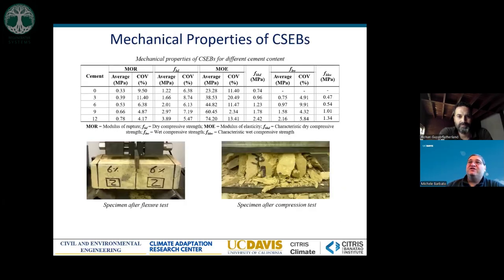And then we started investigating the mechanical properties, and we are interested in several different elements. Obviously, compressive strength, modulus of rupture, which is a measure of the tensile strength and the brittleness of the material. And then we are also interested in two different compressive strengths. Due to the nature of this material, where the clay is able to absorb and release humidity, the mechanical properties are highly dependent on the amount of water that is trapped inside the material. And so we wanted both the dry mechanical strength and the wet mechanical strength because they are both connected with different levels of performance.